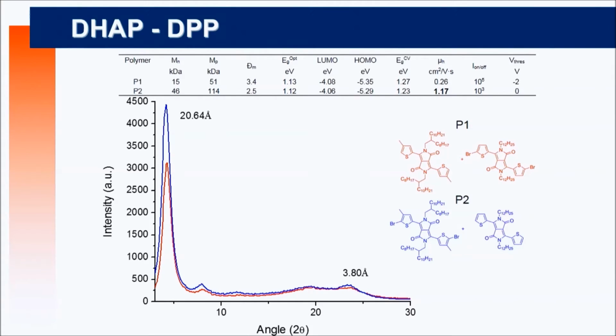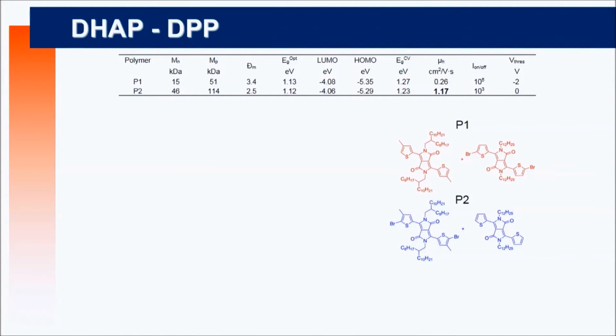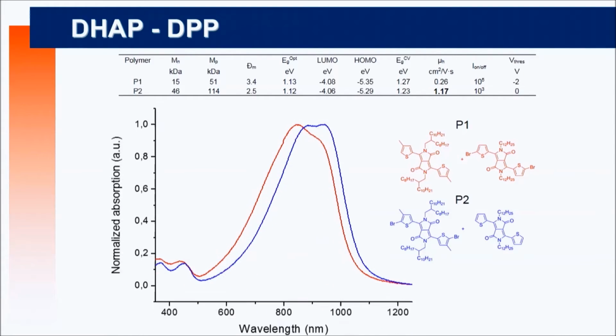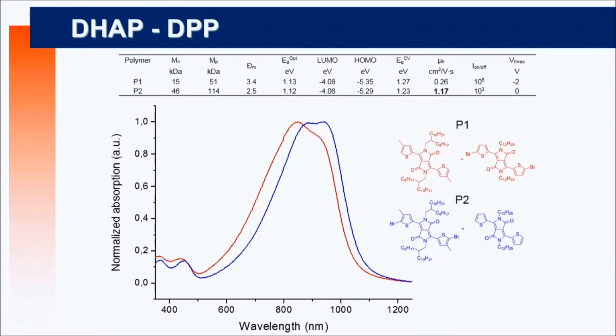With Yuning, look, we got similar results here. If you polymerize this with that, you get the polymer P1. If you polymerize this with that, in principle, you get the same polymer. However, if you polymerize with the bromo and the methyl group here on the CH bond here, you get a mobility up to 1 and a number average of 45. If you polymerize this unit with the bromo and non-protected group here on the methyl group and CH, you get a mobility of 0.2 and a number average of 15. So it's not exactly the same polymer depending on how you choose your monomers. Okay, so you have to be careful. It's not the same UV-vis absorption spectrum. So it's not exactly the same polymer. So that has been done with Yuning, showing that it's possible to reach mobility up to 1 from polymers prepared from direct heteroarylation polymerization. So yeah, it's good.